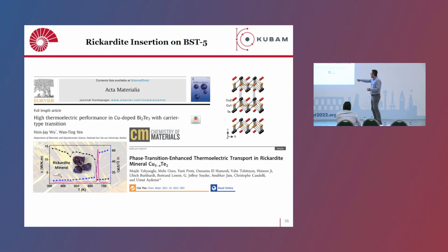Why? Because copper is a mobile ion in copper telluride as well. It has high ionic mobility. It can diffuse easily into bismuth antimony telluride, perfectly fine. And we also have tellurium. That's good because the main material also has tellurium, which means if there is any loss of tellurium, this can compensate for the loss as well. So these were two different aspects that we introduced into the structure, and we saw that this is really working quite nicely. We haven't published this paper yet. We are just writing it. It's a very good idea.